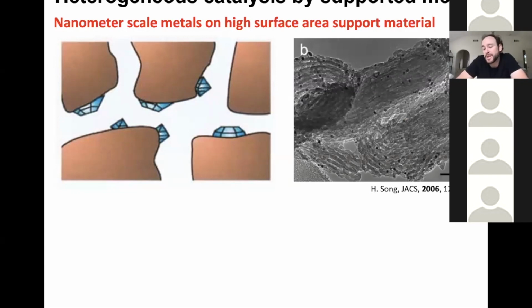And the reason you want a really high surface area material is because you want to be able to load this with a lot of nanometer scale active metal species. So within a catalyst, you often have a support, which on a 0th order approximation is simply the carrier for then your active species, which is usually on the scale of some nanometer size metal or metal oxide particle. So in this cartoon, you can see maybe a little better depiction of it over here. This is a classic SBA 15 material. So you see mesopores going through this. This is a silica. And then these dark spots in here in this TEM micrograph are metal particles, I think platinum in this case, loaded inside of this system.